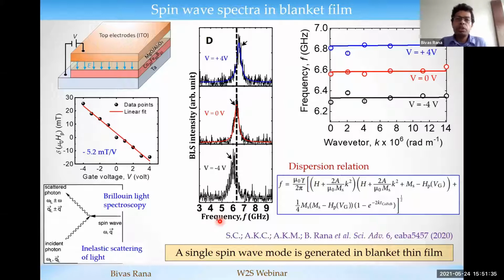Here we applied the same method, to show that these VCMA induced nano channels can be used as a magnonic crystal. First we tried to see how the spin wave behaves in the case of only a blanket thin film, where we only change the perpendicular anisotropy by using a top gate electrode made of ITO, which is transparent. To measure the spin wave, we use the Brillouin light scattering technique. As you can see, when we systematically change the gate voltage, we systematically vary the spin wave frequency because the perpendicular anisotropy is changing.